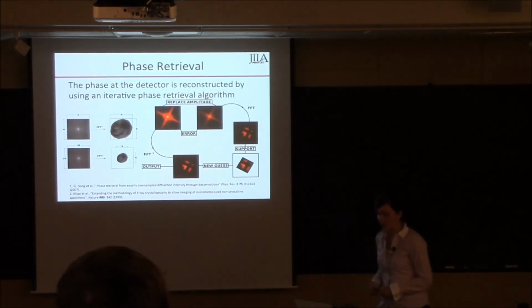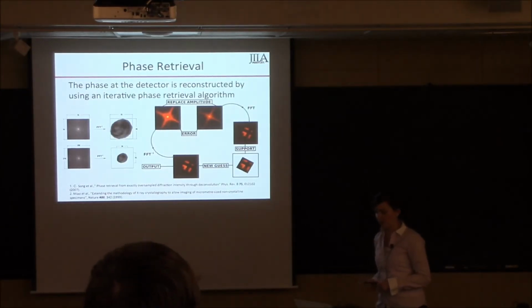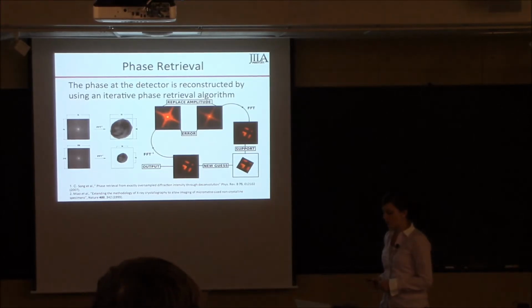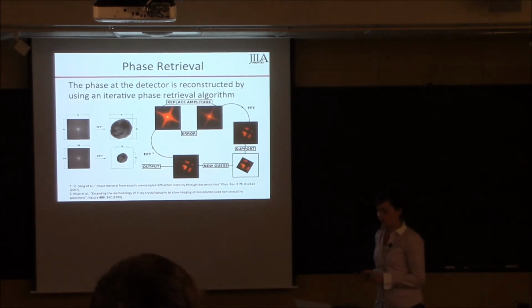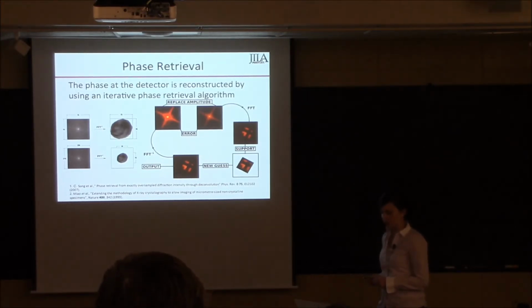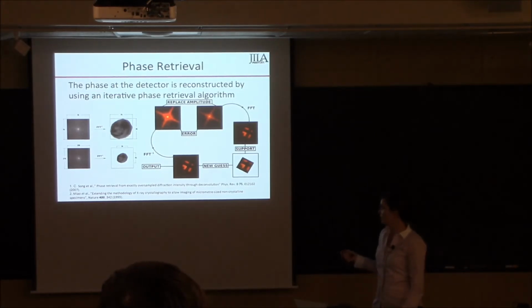Okay, so now what kind of samples can we look at, and how do we actually get the phase? Well, first of all, in order to reconstruct anything, we need to make sure that the diffraction pattern is oversampled. This means that the intensity is being sampled at twice the Nyquist frequency, which in the image plane corresponds to the image taking up a quarter of the total area of the field of view.